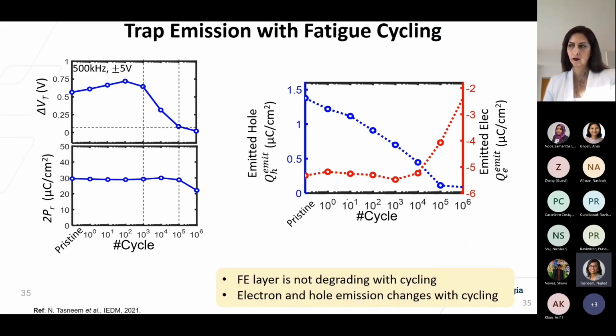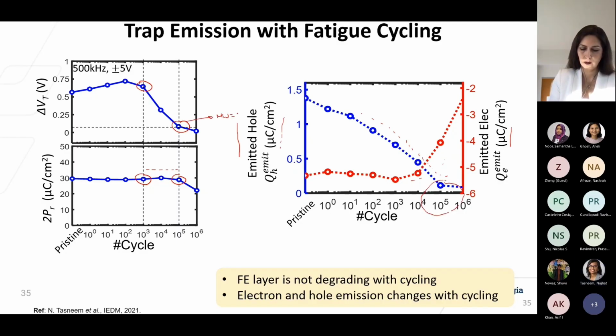So we tried to represent these phenomena quantitatively by these plots over here. The first plot shows that the memory window starts degrading at around 10^3 cycles. It becomes almost 0 at around 10^5 cycles. Interestingly, between 10^3 and 10^5 cycles, the 2Pr value of the FFET remains almost constant. Again, what ends up changing is the amount of emitted hole and emitted electrons, and both of these values monotonically decrease as we keep on increasing the number of cycles. More specifically, the amount of emitted hole actually becomes 0 at around 10^5 cycles, which is the same point where the memory window also closes. So these results indicate that it's not the FE layer, rather the electron and hole dynamics, specifically the hole emission, that plays a significant role in FFET's performance with fatigue cycling.